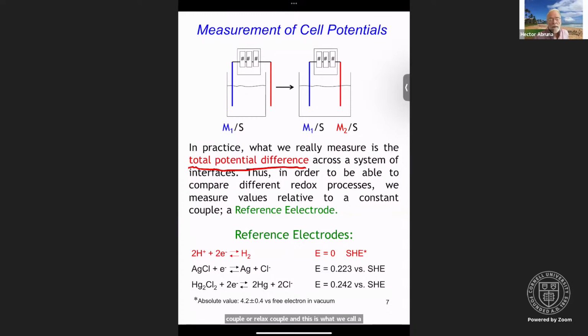And so in most electrochemical measurements, you will have a working electrode, which is the electrode at which the reaction that you're interested in takes place, and then a reference electrode that tells you where you are energetically relative to some known quantity. The more common reference electrodes, so here's the standard hydrogen electrode, 2 protons plus 2 electrons going to hydrogen. This is arbitrarily defined as 0 volts and independent of temperature. There have been some estimates as to its absolute value. It's roughly 4.2 plus or minus 0.4 volts versus free electron in vacuum. That gives you some sense of correlating potentials in solution to potentials in vacuum, and that's a very powerful comparison to make.